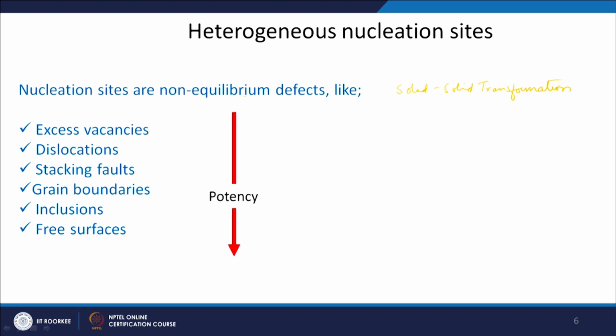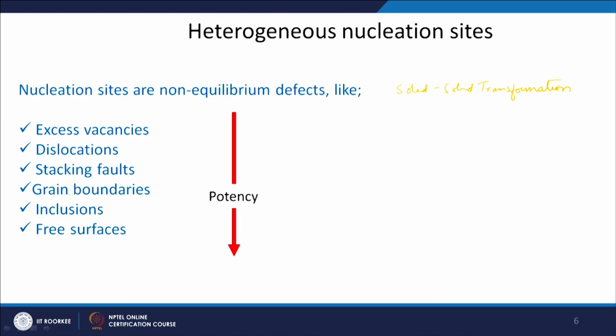So, nucleation sites are the non-equilibrium defects. You have excess vacancies. Vacancies are equilibrium defects, but when you have excess vacancies more than the equilibrium vacancy concentration, that is not an equilibrium condition, so we will call them non-equilibrium defects. Equilibrium vacancies are thermodynamically required to be there. If you have excess vacancies, that can act as a heterogeneous nucleation site. Dislocations can act as heterogeneous nucleation sites. Stacking faults are there, grain boundaries are there, inclusions are there. Inclusions are already present on which you can have another phase forming, or you can have free surfaces on which the nucleation can take place.